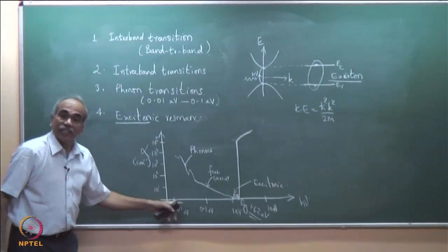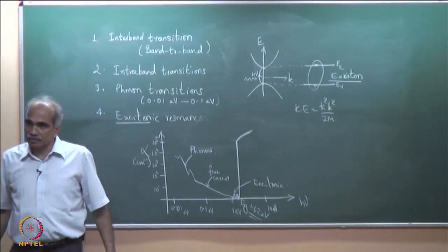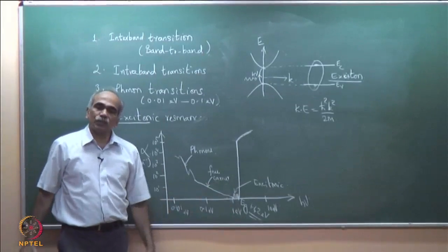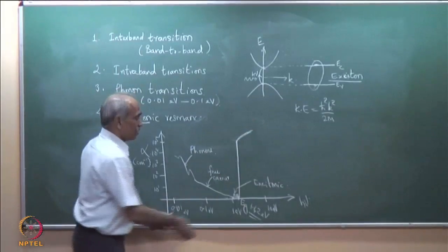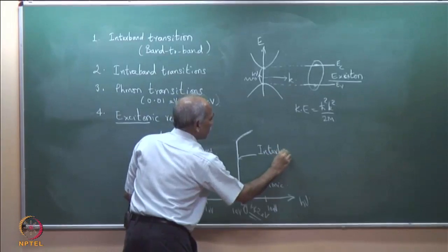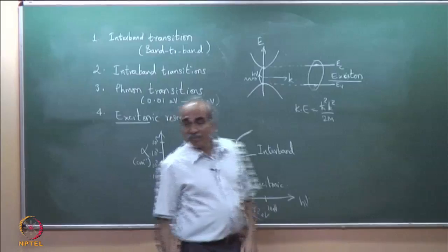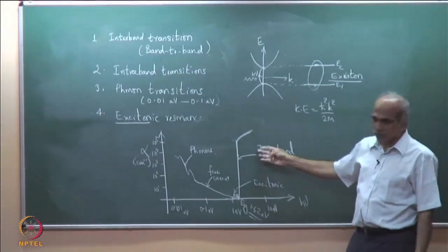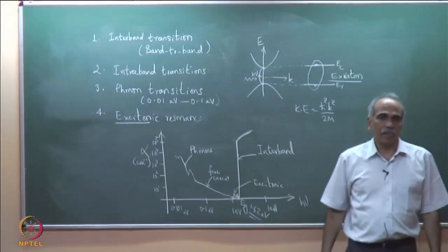because the energy range here corresponds to that of phonons, that is creating vibrations in the lattice. So, energy is spent in creating lattice vibrations directly. And this is due to interband. So, in this complete spectrum we see all the 4 points which I have written: interband, excitonic, free carrier and phonon transition.